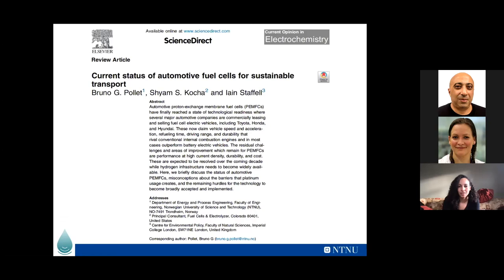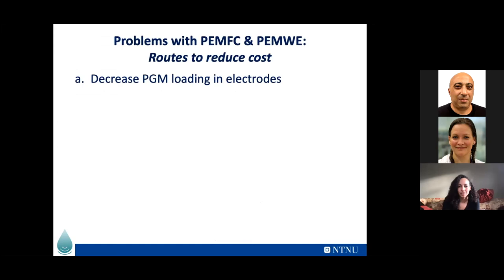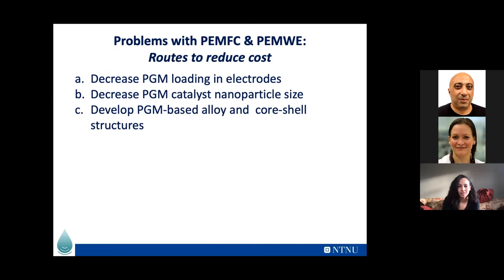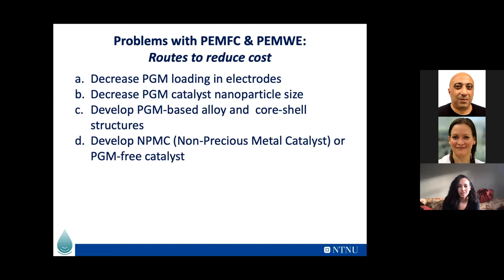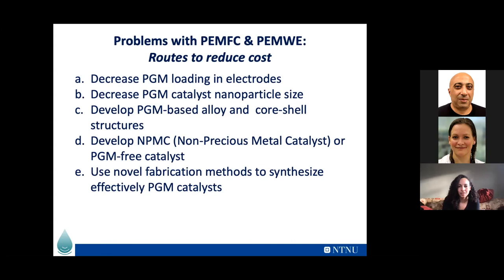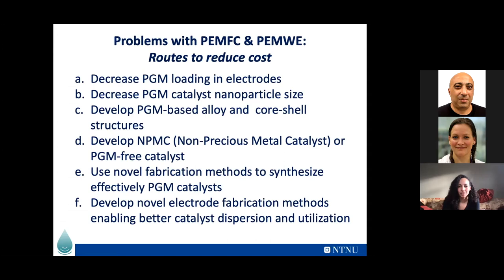Okay, so now there are different ways of reducing the cost. If you're focusing on the catalyst, you can decrease the PGM loading on the electrode, decrease the nanoparticle size, or develop new types of PGM-based alloys or core-shell structures. You can move completely from PGM catalysts to non-precious metal or PGM-free catalysts. You can also look at novel fabrication methods to synthesize efficient catalysts, and at other systems to develop new types of electrode fabrication for PEM fuel cells and PEM water electrolyzers. What we want there is better catalyst dispersion and also utilization, which is important in this area. So there are different ways.